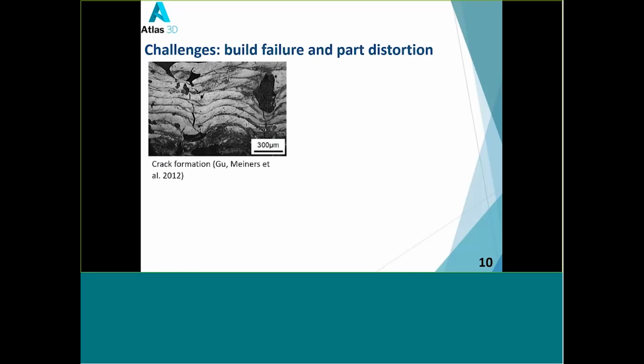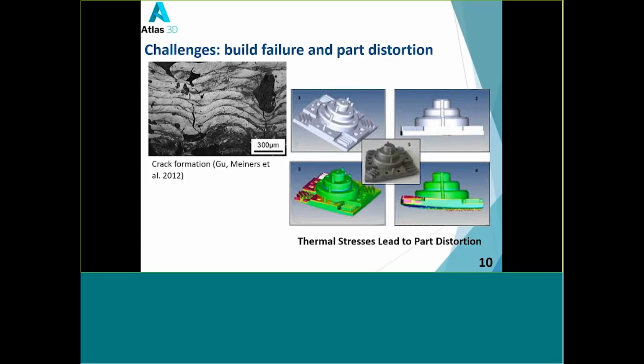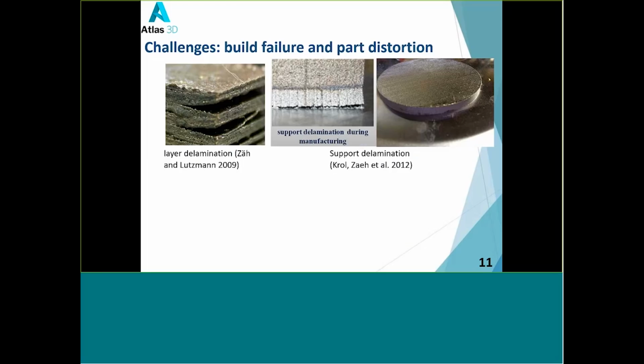However, there are also lots of challenges in the metal AM process. Because in all the metal AM process, we need to use either laser beam or electron beam to melt the metal feedstock, and the thermal gradient and the cooling rate in metal AM process is usually very large. And this will induce lots of thermal stresses in the part. And the thermal stresses usually will cause the crack. And in a global view, the thermal stress will cause the distortion, thermal distortion of the part, and making your part out of specification. And also the other problem is the delamination, both delamination in the part and the delamination of the support structure from the build platform.